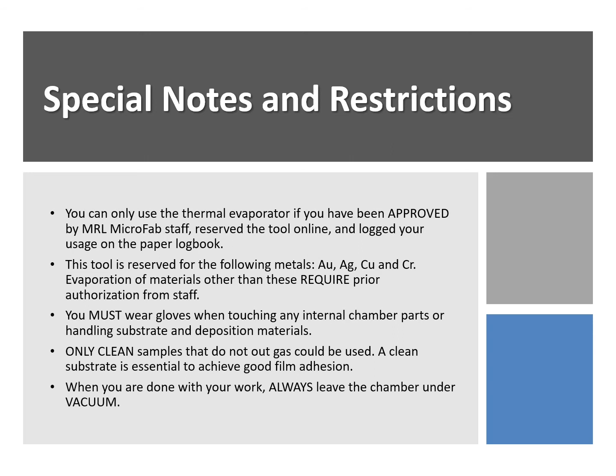You must wear gloves when you need to touch any parts inside the chamber, or when you handle your substrate or your deposition materials. Only clean samples that do not outgas can be used for this deposition process. A clean substrate is very important for good film adhesion. When you are done with your work, please leave the chamber under vacuum. Pump down the chamber. Do not leave it under atmosphere.